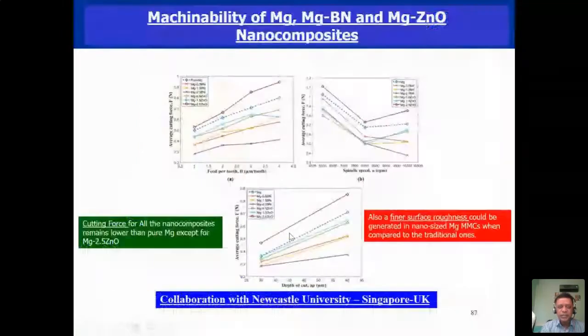We also sent some other nanocomposite samples to the University of Newcastle at their campuses in the UK and Singapore. And they found that the cutting force for all the nanocomposites remains lower than for pure magnesium, except for one composition.